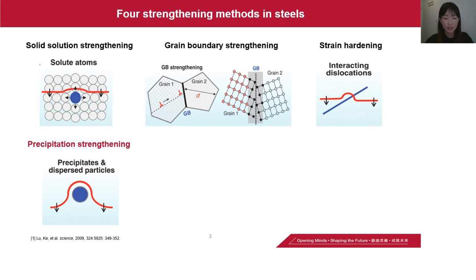There are four strengthening methods often used to strengthen steels. They include solid solution strengthening, grain boundary strengthening, strain hardening, and precipitation strengthening. These methods aim at prohibiting the dislocation mobility. Precipitation strengthening is recognized as the most effective method to strengthen steels by introducing second-phase precipitates.